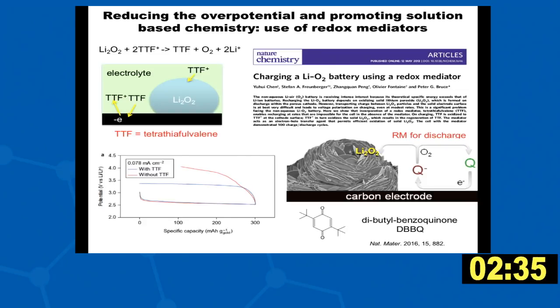So this is on charge without the mediator, and with the mediator, you can see there's a significant reduction of the overpotential between discharge and charge, which then directly relates to an increase in efficiency of the battery. So this is a charge one. For discharge, they proposed a benzoquinone, so DBBQ, which again does the same thing.